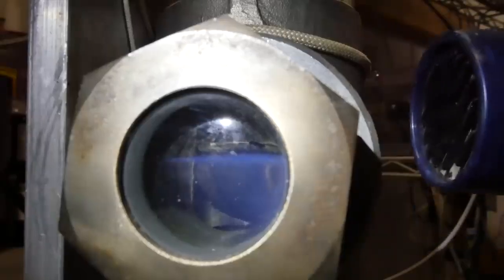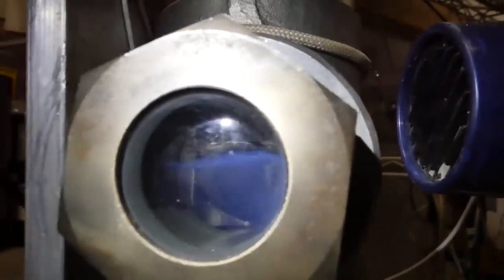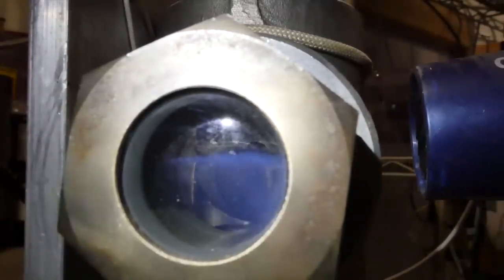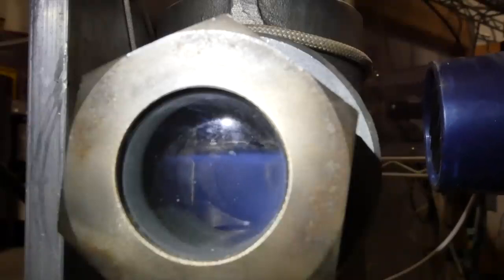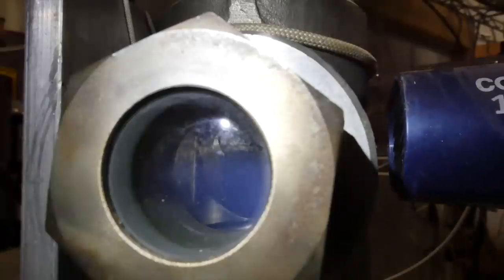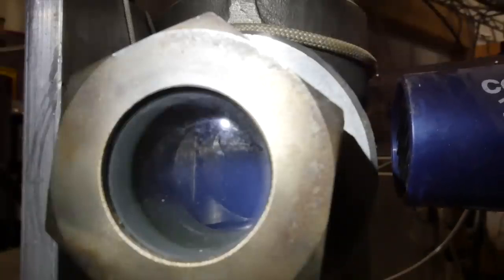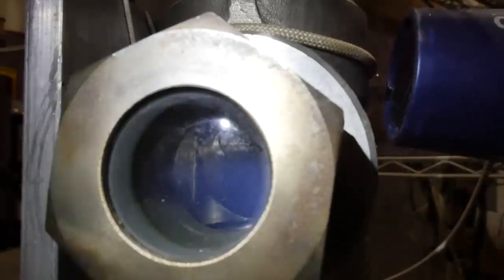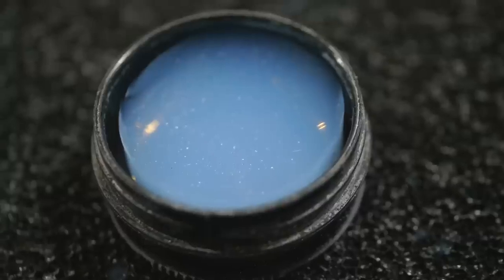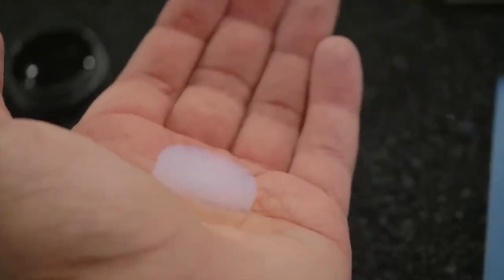As we approach the critical point, the surface of the liquid becomes kind of blurry. Weird, huh? That is like weird waves in there. Yeah. I'll speed it up so you can watch the surface disappear altogether. You're now looking at the supercritical fluid of CO2. In this state, the CO2 can be vented without affecting the solid structure, and what you're left with is aerogel.